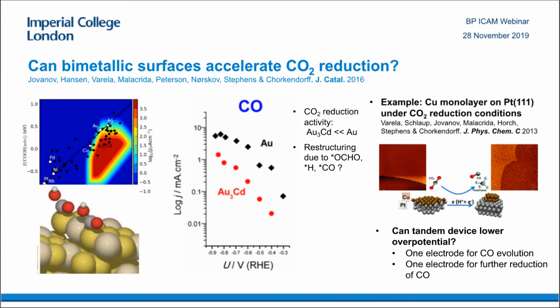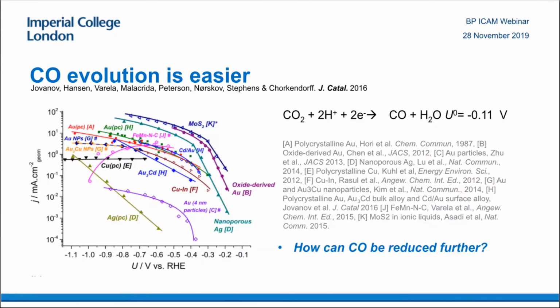So one way of getting around this constraint is to look at what we call a tandem device. You'd have one electrode for CO evolution, another electrode for further reduction of CO. It turns out for CO evolution, this is a summary of many different studies in the literature. You can get quite reasonable current densities, quite close to the thermodynamic potential, about minus 0.11 volts. So you can make CO quite efficiently.